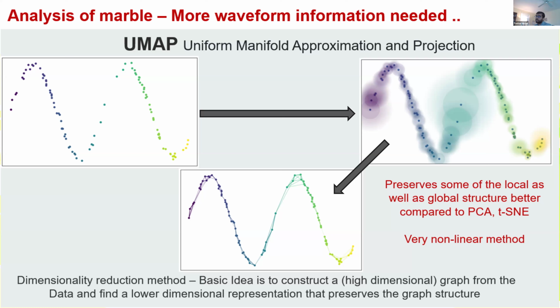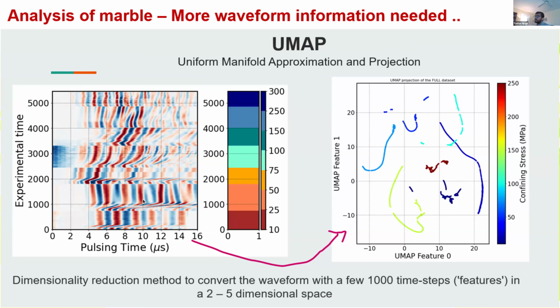And what UMAP tries to do, and does fairly well compared to a lot of other algorithms, is that it preserves the local and global structure of the graph pretty accurately. So as a result, rather than giving it the full waveform, we can take our waveforms and project them into 2-dimensional space in UMAP, which is shown on the right. If we color it by the stresses, we can see that this 2-dimensional projection is already pretty good in distinguishing where we are with regards to confining stress.